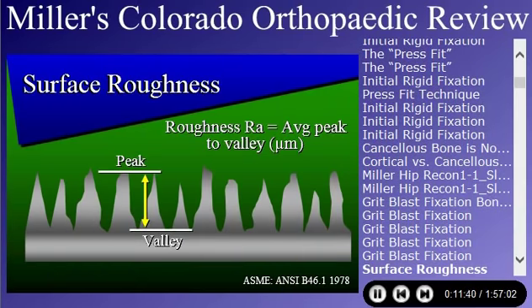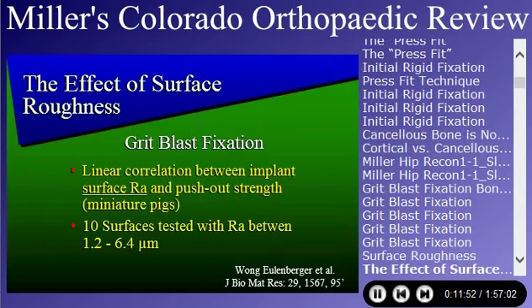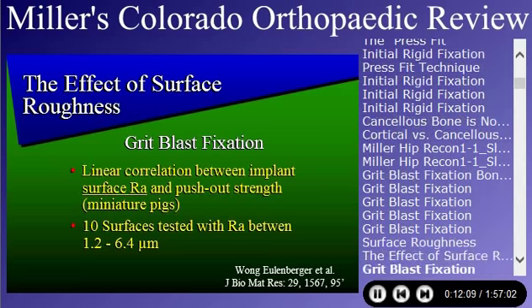The surface roughness is the important critical factor in describing how well these grit-blasted on-growth stems work. The roughness is, by definition, the average between the peak to valley of the surface. And the studies have shown that there's a linear correlation between implant surface roughness and push-out strength, as opposed to porous-coated surfaces where pore depth is the critical factor. The critical factor in grit-blasted stems is the surface roughness. The rougher the stem, the better bone on-growth you're going to get, and that kind of makes intuitive sense.